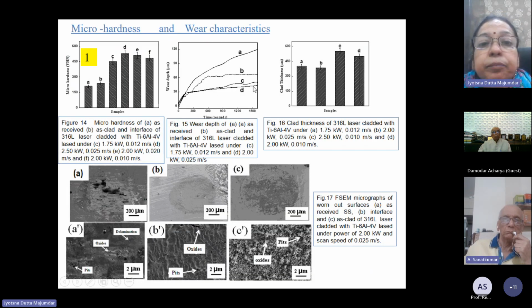When we measured other properties like microhardness, we saw that microhardness was higher than as received. Not because of the material itself, but because Ti6Al4V is highly refined when you develop it on wrought stainless steel. The stainless steel had a wrought structure, but on the surface the Ti6Al4V was laser melted, so the microstructure was highly refined. As a result there was improvement in microhardness and also wear resistance to a large extent.